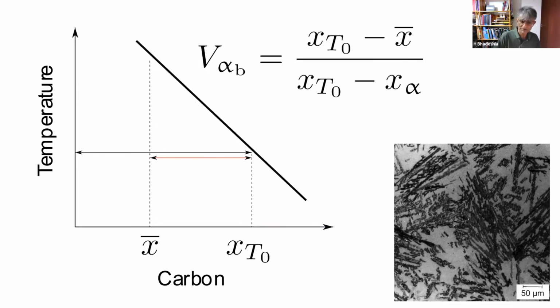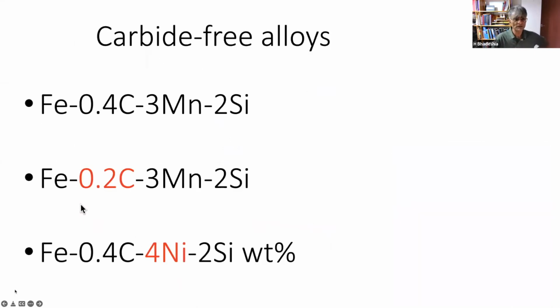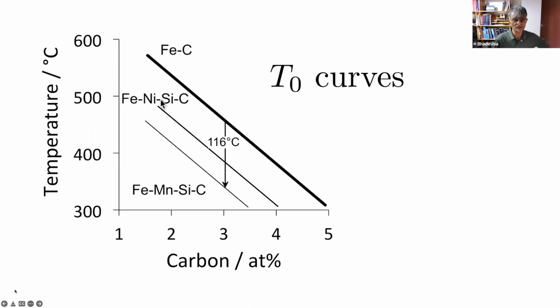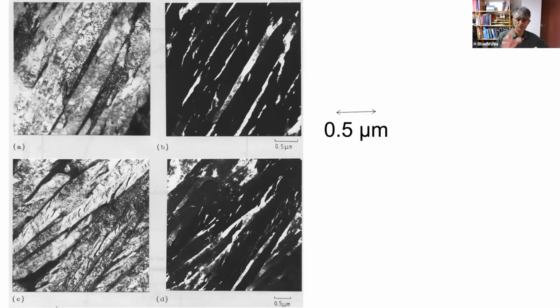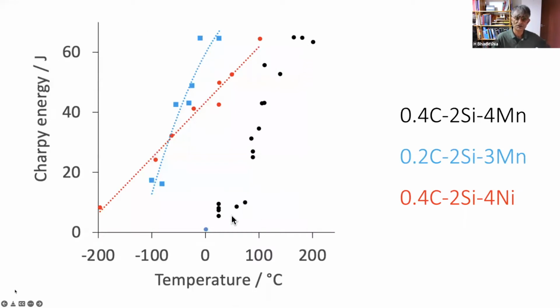Okay? So we designed 2 new steels without doing any experiments, one in which we simply halved the average carbon concentration, and the other one in which we shifted the T0 curve to larger concentrations by substituting for manganese. So if you calculate T0 curves, then you can see that the manganese, the nickel T0 curve is located at larger concentrations. And immediately, you get the right microstructure for both of those new steels, and you shift the ductile brittle transition temperature down by 200 degrees centigrade. Okay, so this was the original set of data, and these are the 2 new steels where we have the ductile brittle transition at cryogenic temperatures.